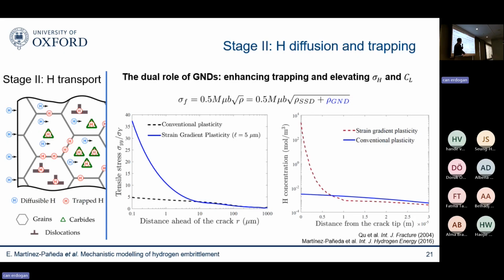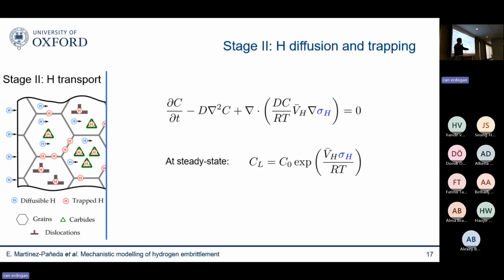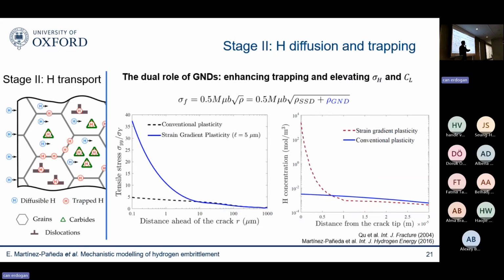strain gradient plasticity. And what you see is that far away from the crack tip, these GND effects are small, you can neglect them. But near the crack tip, because you have very high plastic strain gradients, these GND effects are going to be big, and therefore your stresses are going to be much larger than those that you can predict using conventional theories like von Mises. And this is very important in hydrogen because, taking you back to this equation, we have an exponential term that relies on the hydrostatic stress. So you can see here that the hydrogen concentration is going to be much, much higher near the crack tip. And as you will see later, this is important in order to rationalize the underlying physical mechanisms that drive hydrogen.